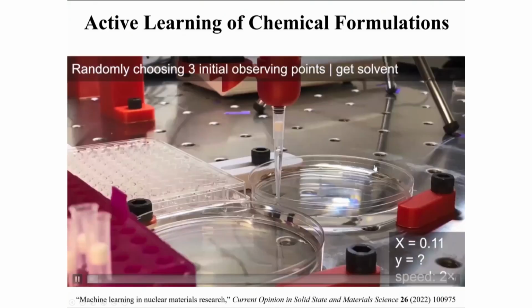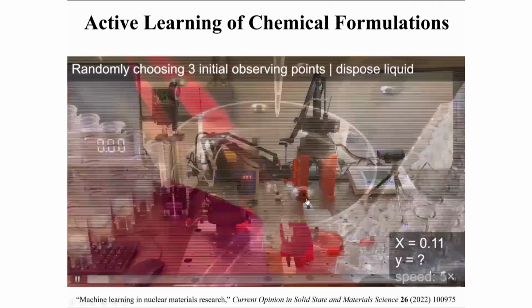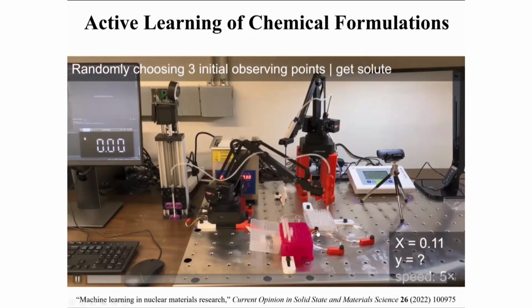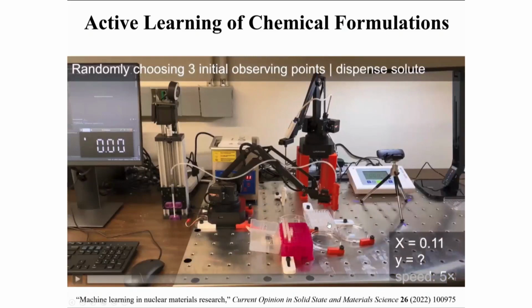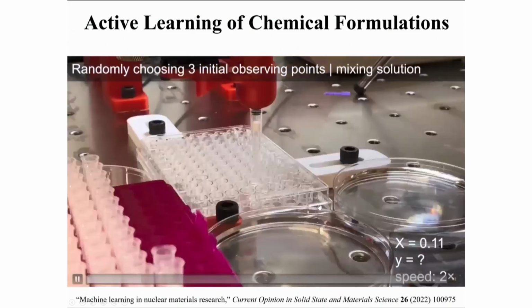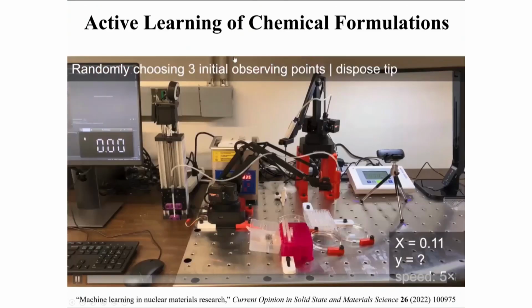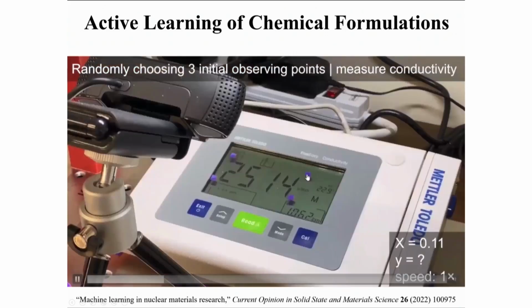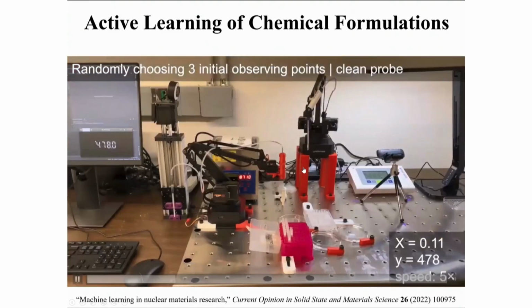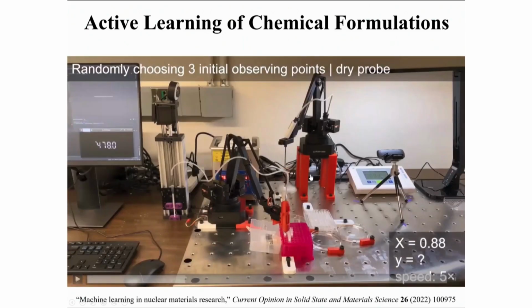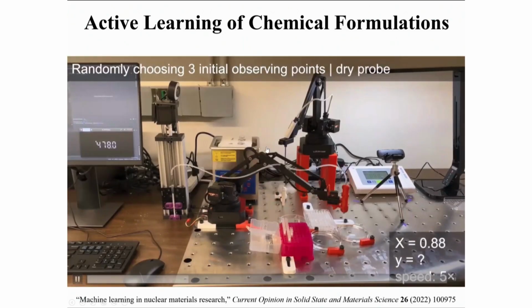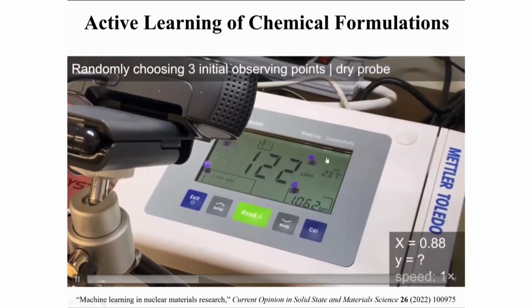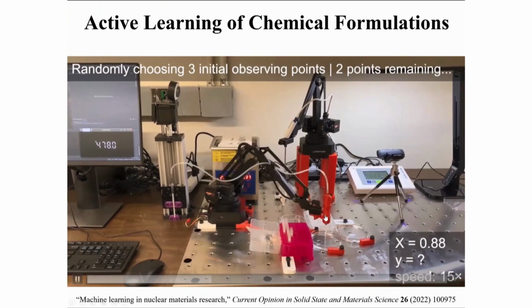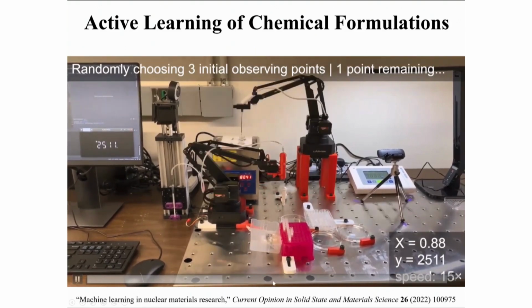To further expand the chemical space, 4 years ago, my student Zhichu Ren built this little demonstration where we are just mixing several salts into solvents and measuring the ionic conductivity. So the goal here is to drive so-called active learning, where you design the next set of automated experiments based on the previous experimental results. So here, after measurement, this conductivity meter is washed, dried, and then a new composition is being made, and then a new measurement is being made.